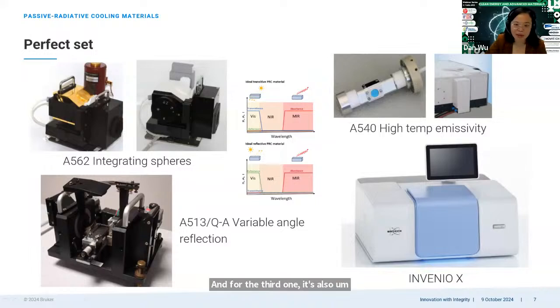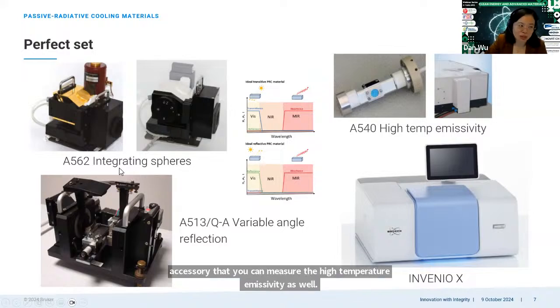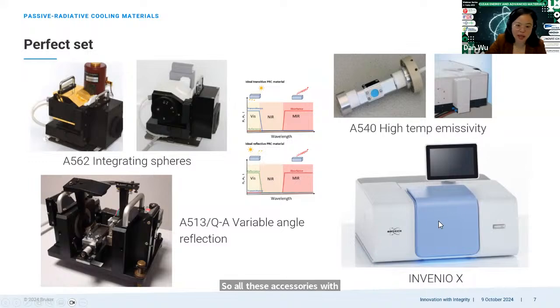Because for some of the materials, you may have a heating effect from either the environmental temperature or very strong solar radiation and so on. So the temperature of the material will also get a little bit higher than room temperature. And for such a study, you will need temperature conditioning of the sample. So here it's also available as an accessory that you can measure the high temperature emissivity as well. So all these accessories with different purposes can be combined with the FTIR easily.